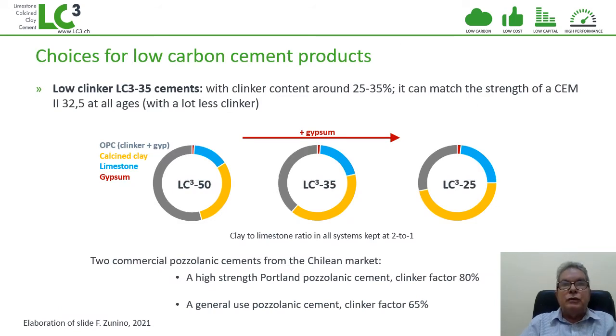But an interesting choice that has come up in the last few months is the possibility of going further into clinker substitution and dropping clinker content down to 35-25% and see what happens. Because as I said before, we're addressing a cement that is for concrete, for high strength concrete. But when you look at the uses of cement, more than 40% of the cement is used only in masonry applications. And in this case, a general use cement would do.